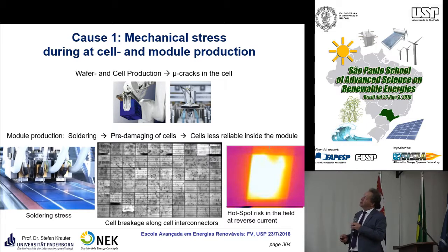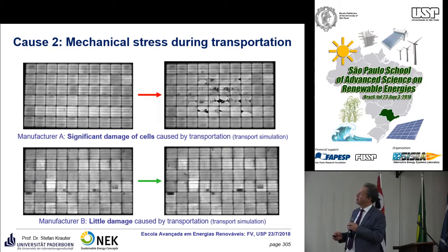Here you see first we start with the production. Here you see what can happen; you can usually identify them by seeing repeating patterns. So this is usually at production. This is a typical pattern which occurs during production in microcracks. This is during transportation. Usually, if the module is vibrating because you transport it horizontally, you have some cracks here. Here, this is a more stable construction.